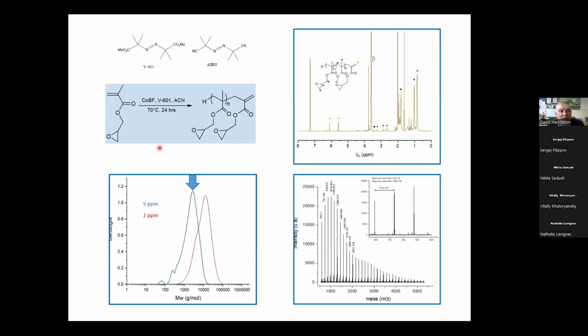So you can do all methacrylates. I've just picked one here. This is a glycidyl methacrylate, which when we use CoBF with a normal free radical initiator, V601 is the methyl ester equivalent of AIBN. We use that because the radical then resembles a methacrylate as opposed to a methacrylonitrile, but you can use AIBN. Half-life is about the same. So reaction conditions would be about 70 degrees over less than 24 hours, but we could leave it for 24 hours. And we'll end up with this polymer structure.